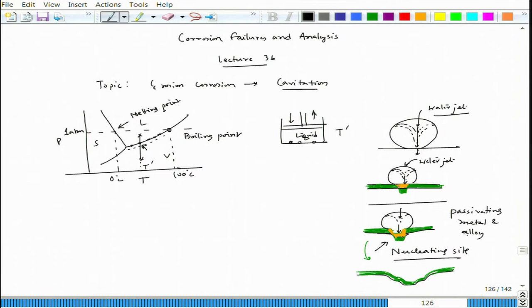Passivating metal and alloy. But if it is not passivating, of course, the passive layer is not breaking, but it will be deformed because of this water jet that is impinging on this particular surface. This is the deformed part. So, now this is an active site, and that would lead to a higher degree of corrosion. So, then this part will corrode to some extent, and the next bubble forms, and then again that bubble collapse happens. Like that, the cycle will move on.